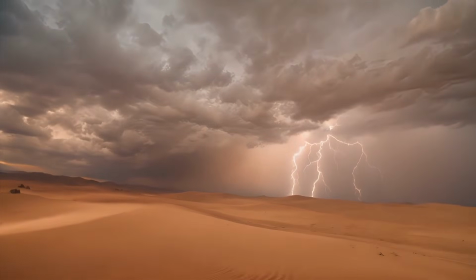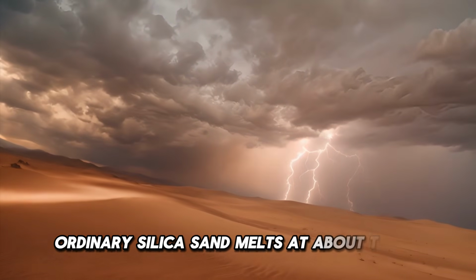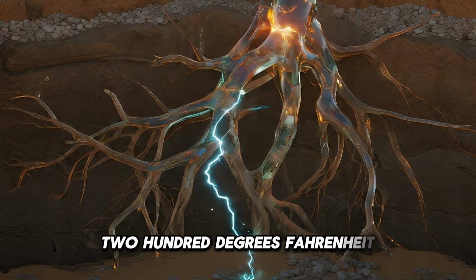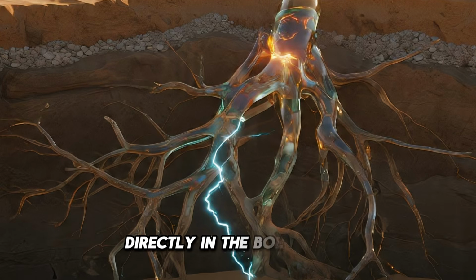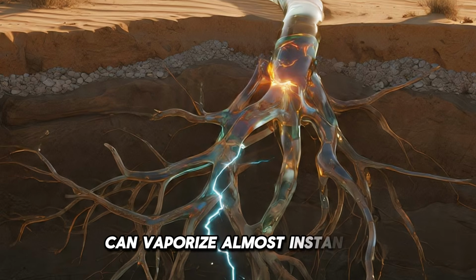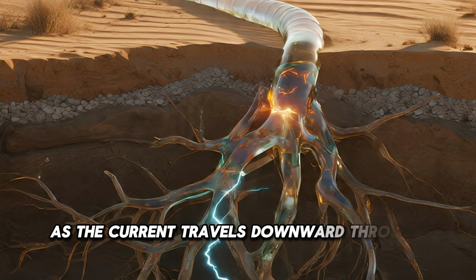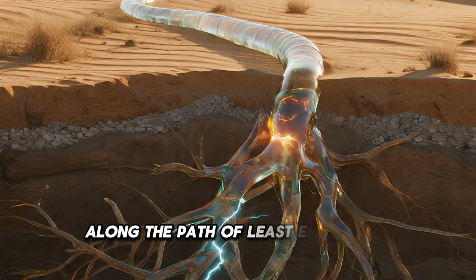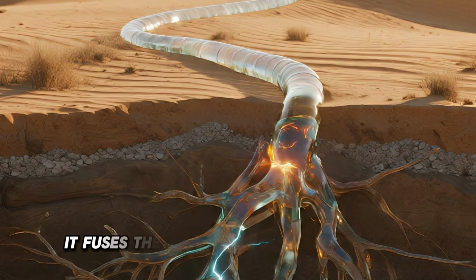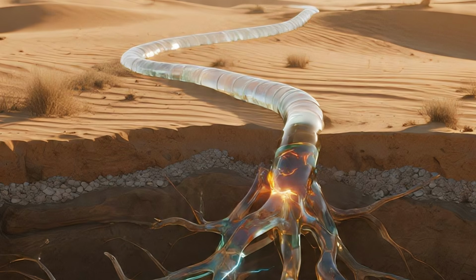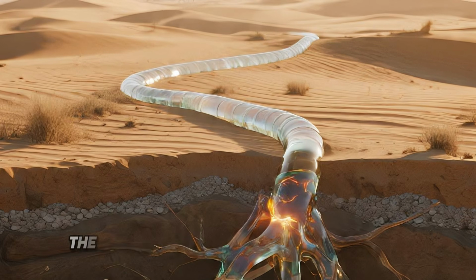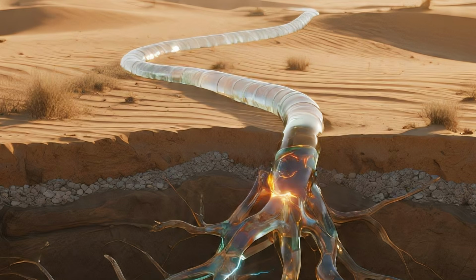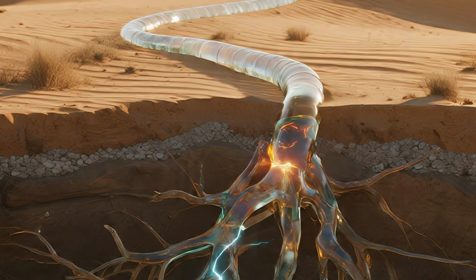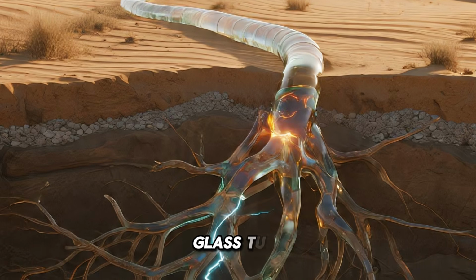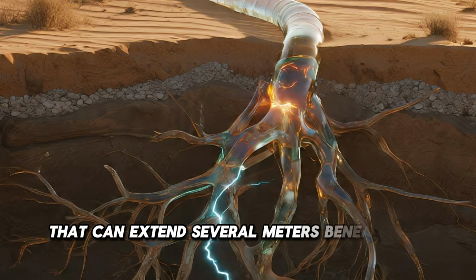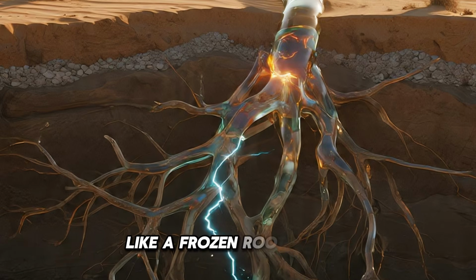of the sun. Ordinary silica sand melts at about 3,200 degrees Fahrenheit, so the sand directly in the bolt's path can vaporize almost instantly. As the current travels downward through the ground along the path of least electrical resistance, it fuses the surrounding grains of silica. The energy quickly fades, the material cools almost immediately, and a remarkable structure remains: a hollow, branching glass tube that can extend several meters beneath the surface like a frozen root system.